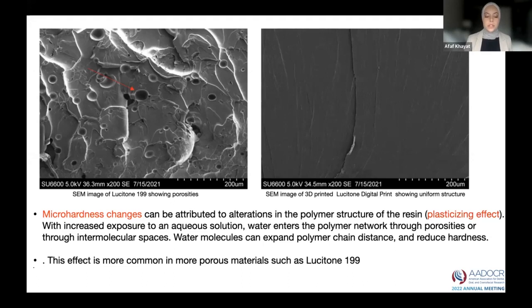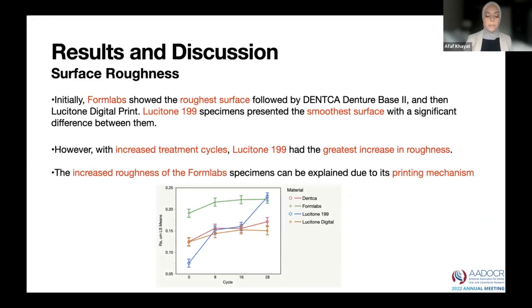For the surface roughness, initially Formlabs showed the roughest surface, followed by DENTCA Denture Base II, and then Lucitone digital print. Lucitone 199 specimens presented the smoothest surface, with a significant difference between them. However, with increased treatment cycles, Lucitone 199 had the greatest increase in roughness. The increased roughness of the Formlabs specimens can be explained by its printing mechanism.